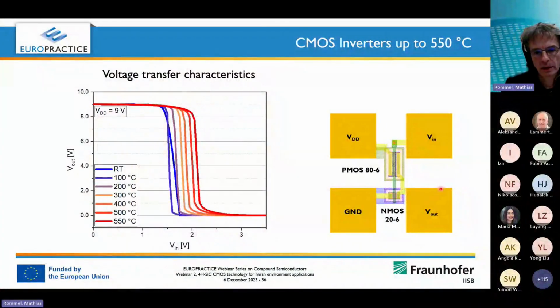Another example is an inverter with these two transistors I showed before. And you can see you get basically a very nice transition, but of course also not stable or identical with temperature. And this kind of more strange transfer characteristic for room temperature is due to the fact that at these temperatures the PMOS is still not fully open at these voltages, and that's also why it's even good to operate it at higher temperatures and not at room temperature. But of course it still works and gives at least a decent voltage transfer characteristic. And of course one can also optimize it for room temperature conditions with different geometries.